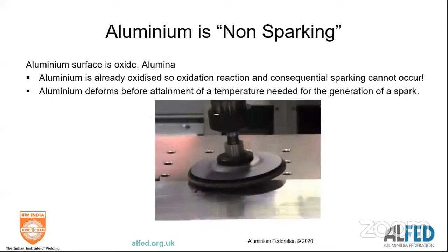Just pick out a property of aluminium. Aluminium is non-sparking, because when a metal sparks, what happens in essence is the pure metal is burning in oxygen to produce an oxide. Because aluminium will instantly oxidize, very rarely do you see sparking of aluminium, because it forms an oxide instantaneously.